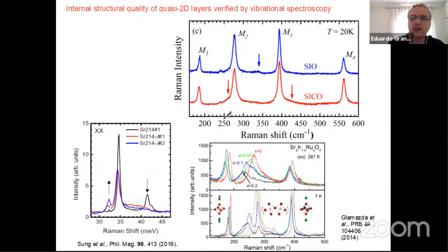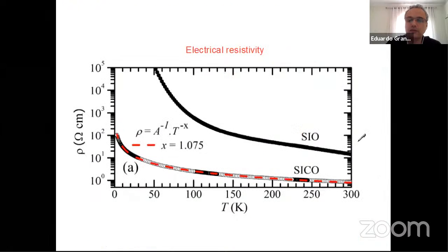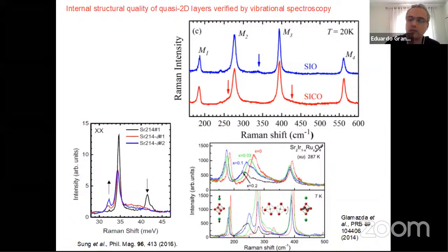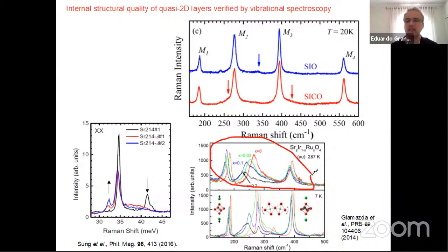We performed vibrational spectroscopy to check if the internal structural quality of the layers is preserved. The Raman spectrum, the inelastic light scattering from these samples, is of very good quality. The phonons that we show in the Raman spectrum have pretty much the same width for the pure and for the doped compounds. That's good news. For the cobalt doping, that's completely different with respect to other types of doping, like ruthenium doping in the system, that changes completely the vibrational spectrum of the system. Here, in this case, it didn't change too much. So apparently, we can safely say that the cobalt substitution did not change the structure significantly.